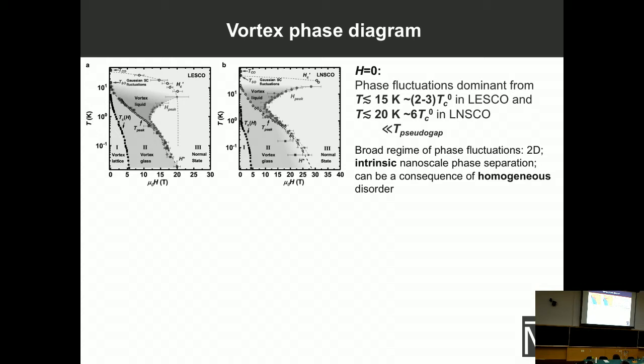Nevertheless, this is a very wide, very broad regime where phase fluctuations dominate, and this can be attributed to several factors. One is the effective two-dimensionality of these materials, where one expects to have a BKT transition at zero field. Also, we know that in these materials we have intrinsic nanoscale phase separation. We have these short-range charge and spin stripes, and we know that in general, in the presence of competing interactions, one can have nanoscale intrinsic phase separation, even in the absence of disorder.